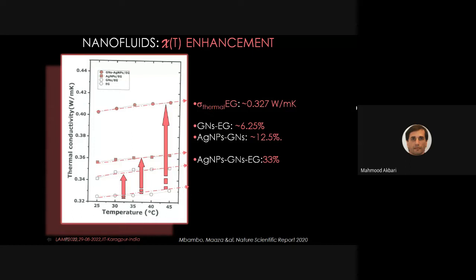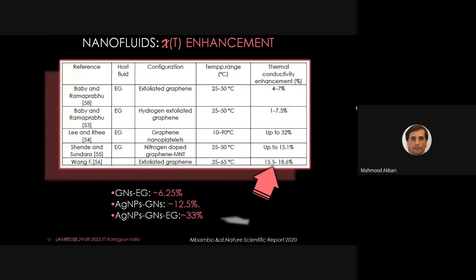Now, if we take the silver nanoparticles grafted on the graphene, colleagues, the thermal conductivity is given by the top curve, pink circles. As you can see, relative to the bottom curve, which is pure host ethylene glycol, the standard one, the increase is around 33%, and this is not negligible when it comes to thermoconductivity. It is high. An enhancement of 33% is just very high. Next, please, Prof.